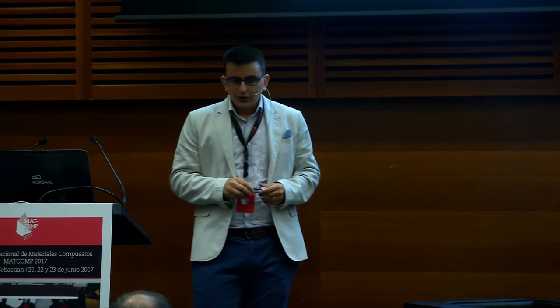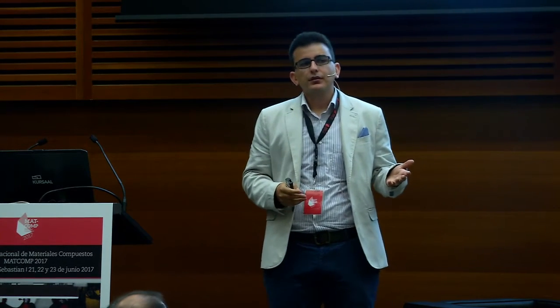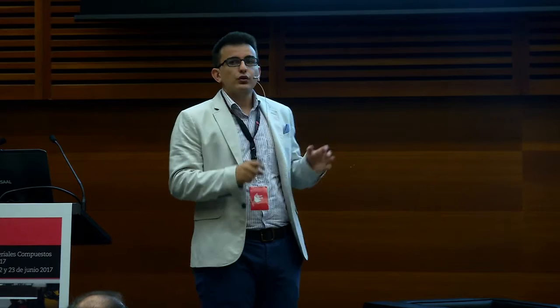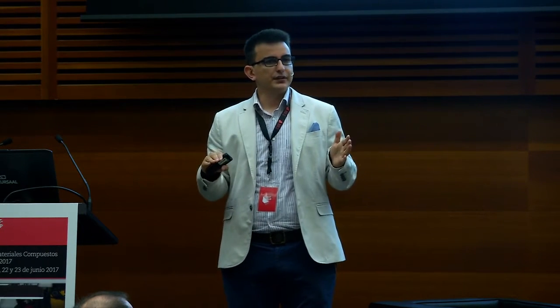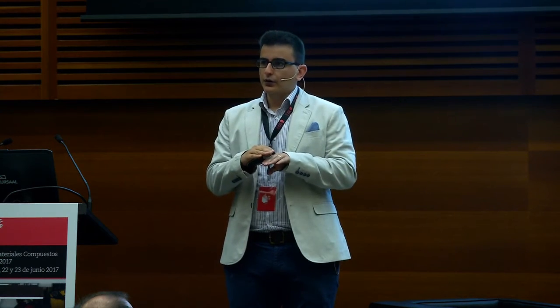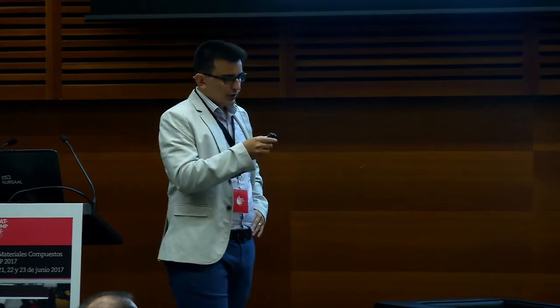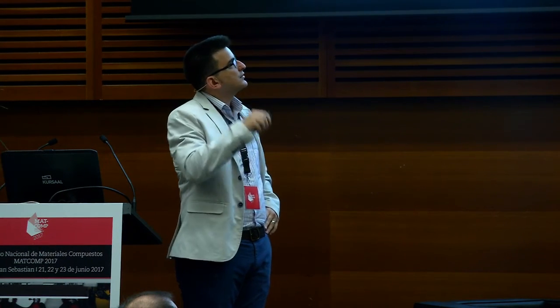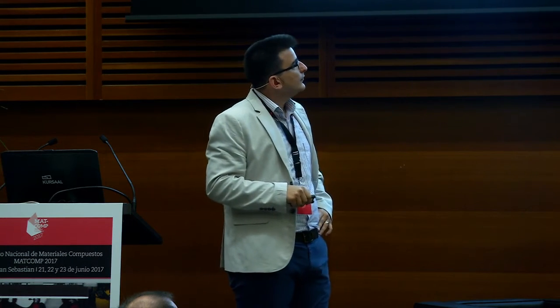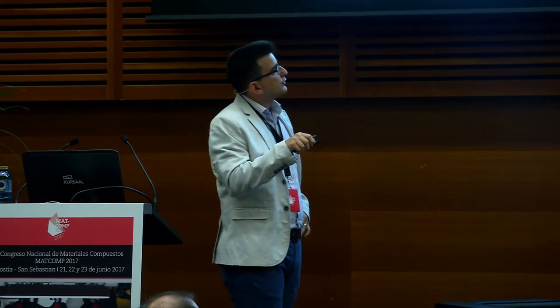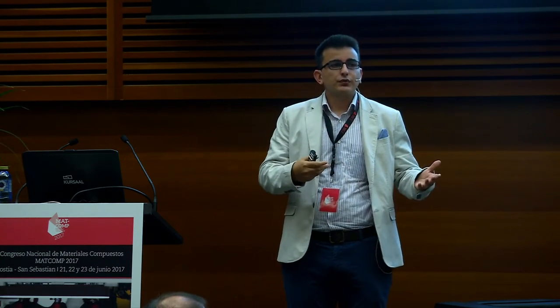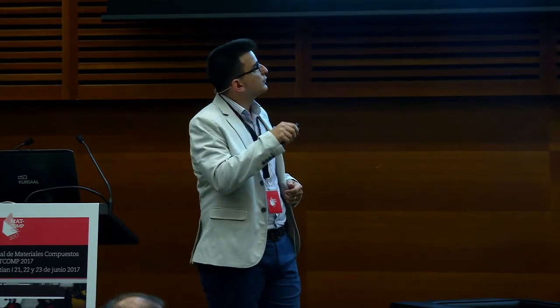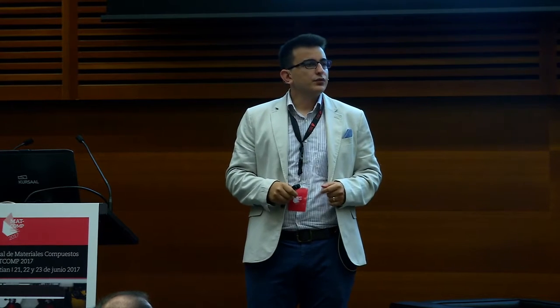Using the process models, we can determine which pulling speed we should use for a specific part thickness. So it's obvious that we have conflicting phenomena here. As industry, we would like to maximize the pulling speed, but on the other hand, we don't want any delamination, or any high cure gradients through the thickness. So this is the plot of pulling speed, part thickness, and centerline degree of cure during the process. For very thick profiles, we have to pull our profile with really slow speed. And for thin profiles, we can use the maximum capacity of our machine.